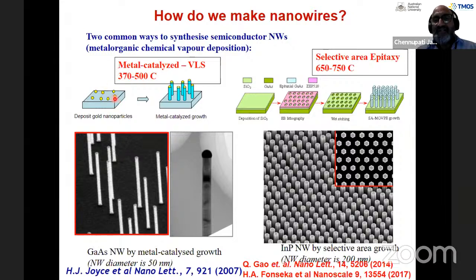Then what happens is that this gold reacts with the gallium in the gallium arsenide. It starts forming this gold-gallium eutectic liquid at around 350 degrees Celsius. So now we introduce the gases needed for the growth of gallium arsenide: trimethyl gallium and arsine in the case of MOCVD, and gallium and arsenic in the case of MBE. They get incorporated as liquid alloy, it gets supersaturated, crystal starts precipitating out, and gold is always sitting on the top. It is like putting sugar into water.